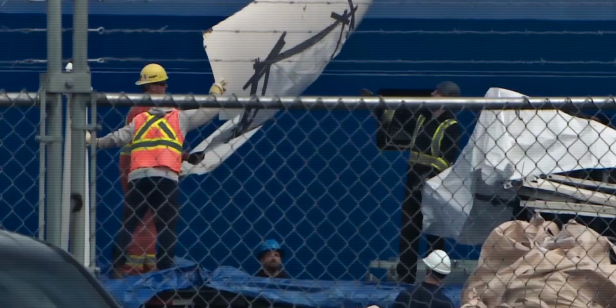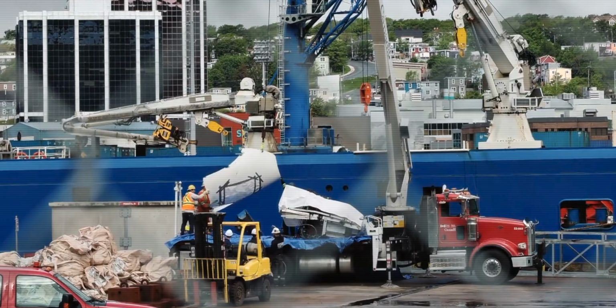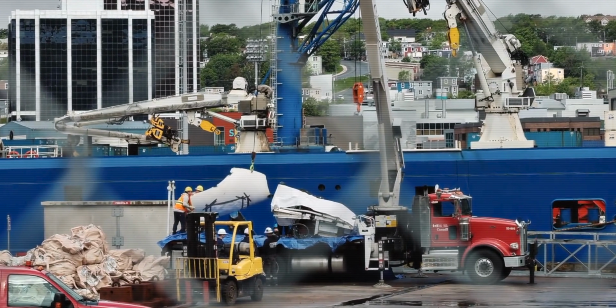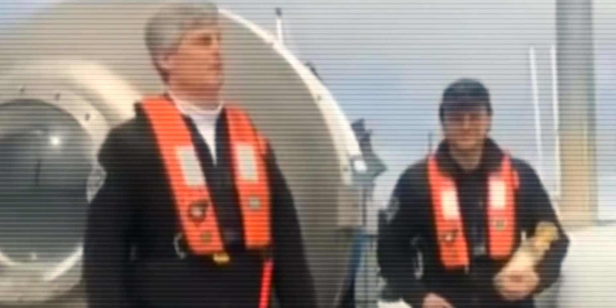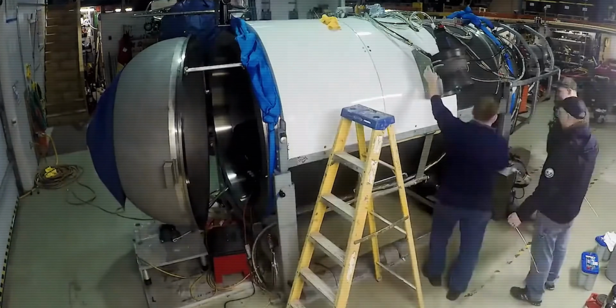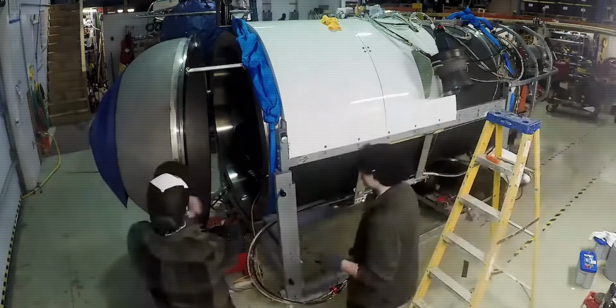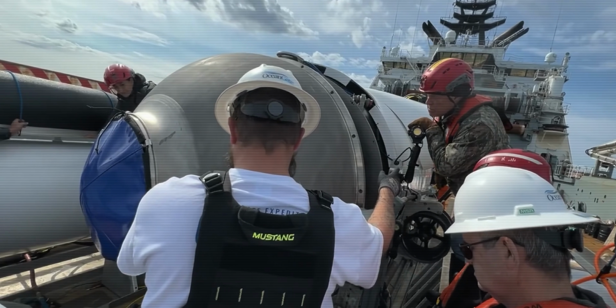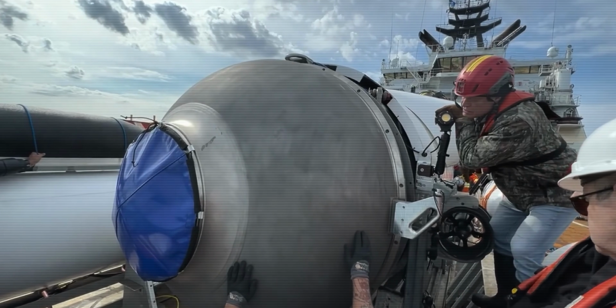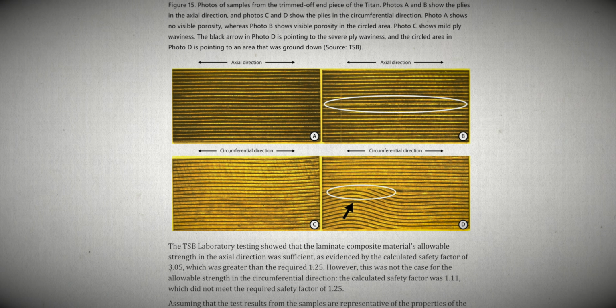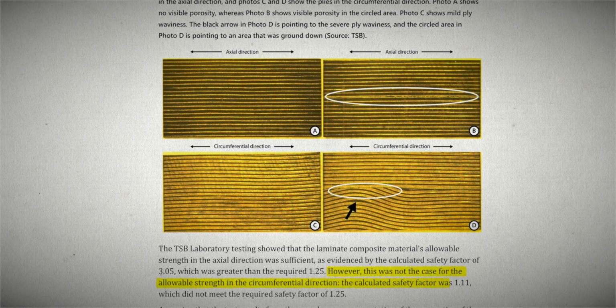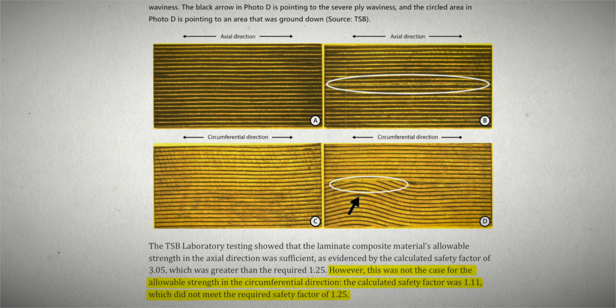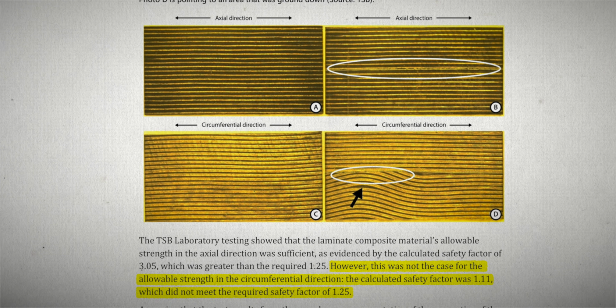The investigation also uncovered another problem. Engineers don't build structures to survive exactly the expected load. They build in extra strength as a safety margin. OceanGate's design called for a safety factor of 1.25, meaning the pressure hull should have been able to withstand about 25% more load than required. Testing showed the finished hull received only about 1.11. That reduced margin did not guarantee failure, but it left the structure with far less tolerance for manufacturing defects, damage accumulation, or unexpected loads.